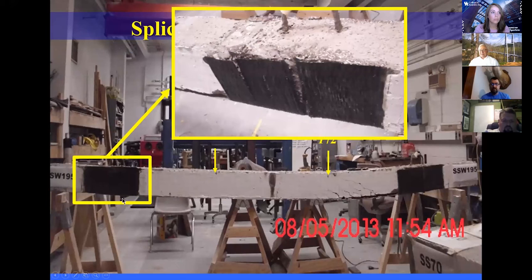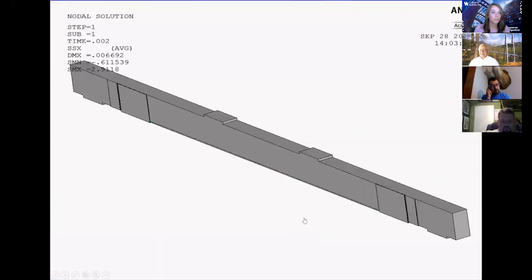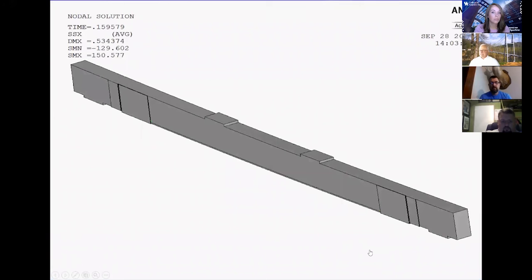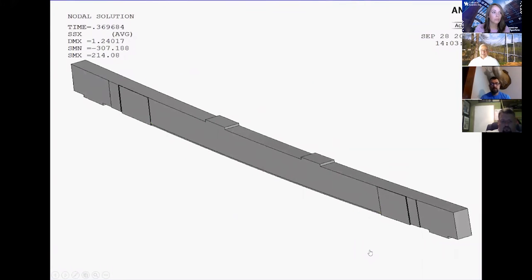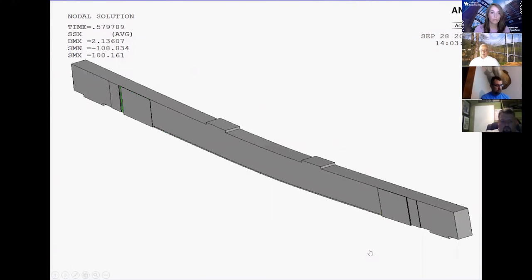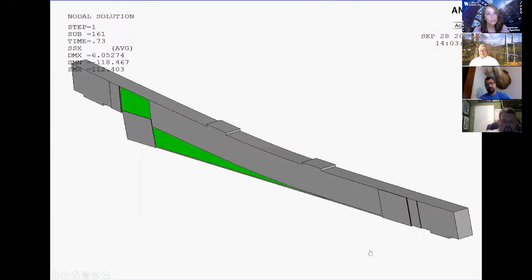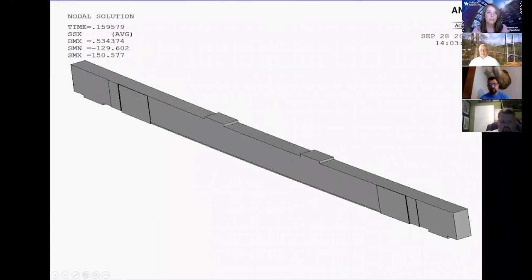this is the failure for one beam where we put some wraps around the ends of the fabric. And now I'm doing the computer testing for it. And actually, you can see it slowly moving. And when this fails in the computer, it actually fails just like it did in the laboratory. So now we are confident with our computer model, and I can test hundreds of these beams very cheaply compared to each one costing us about $10,000.